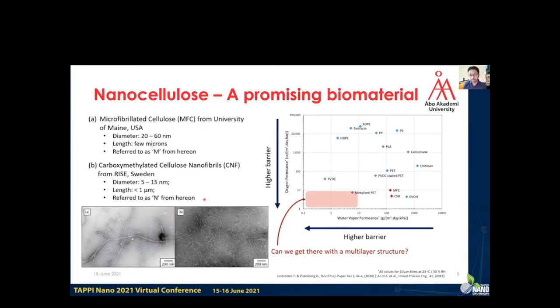And then if you look at the figure to the right, we can see oxygen permeance and water vapor permeance plotted on the Y and X axes respectively. And a lower value means a higher barrier. So the red dots here, MFC and CNF, are the ones that are used in this work, and this is for a pure film. And as we all know, nanocellulose has a very good oxygen barrier, but a rather poor water vapor barrier.